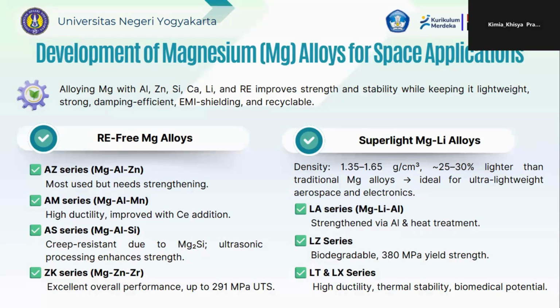while the super light magnesium alloys are about 1.35 to 1.65 gram per cc in density and 25% lighter than traditional magnesium alloys. It is ideal for ultra lightweight aerospace and electronics. The series is LA, LZ, LT, and LX.